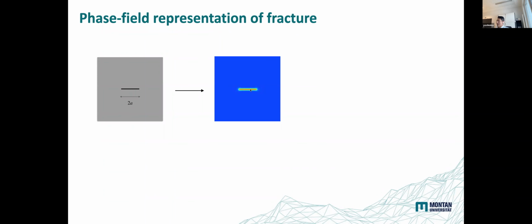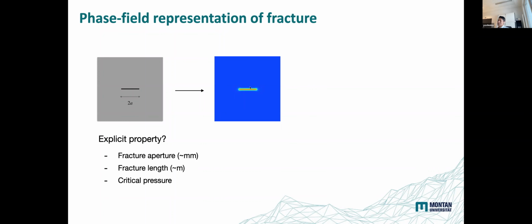And by representing fracture in this diffuse manner, of course, we want to know whether we still can recover explicit properties, such as fracture aperture, fracture length, or fracture critical pressure. And we all know that the fracture aperture is in the order of millimeters, while the fracture length is in the order of meters. And this huge anisotropy is actually what makes the computation of fracture difficult, but we have to make sure that we can recover these explicit properties.